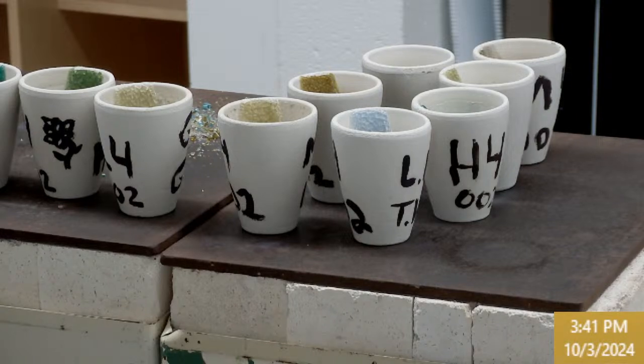It won't hurt. After they've all cycled through those measurements, the glass is usually just warm. You can move them over to the light table and do a little more analysis and handling. Once all that's done, I load them back in, and at some point in the next week or so, go up to 550, hold for an hour or two, then kill the power on the furnace and let it free fall slowly back down to room temperature. And then all the stress just disappears. We have pretty good track records. None of these shatter. I've refined the ingredients to encourage stability in the batches.